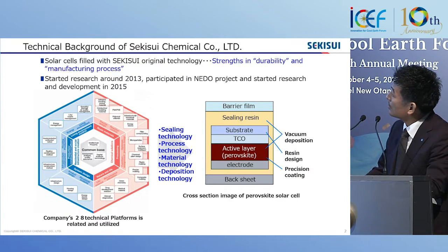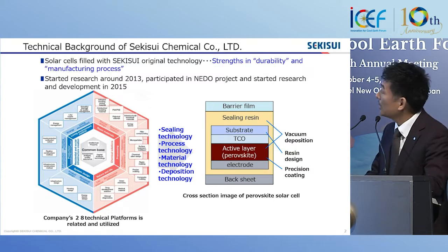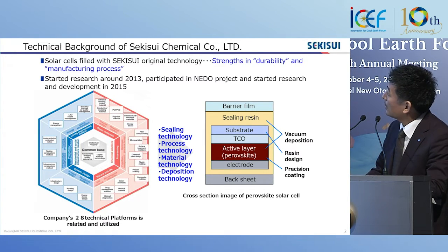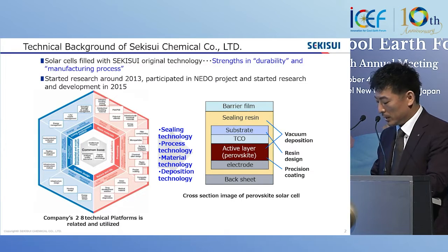As you can see in the right-hand side picture, this is a cross-section image of a perovskite solar cell. Our active layer is a perovskite, which is printed by a roll-to-roll process. It is then sandwiched by a backsheet and a barrier film, with a sealing resin. We have vacuum deposition processes, resin design material technologies, and precision coating technology that we have developed by ourselves.